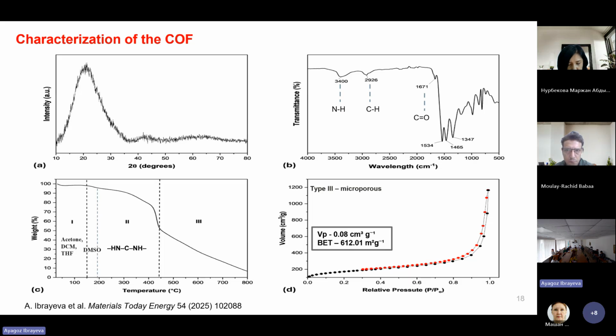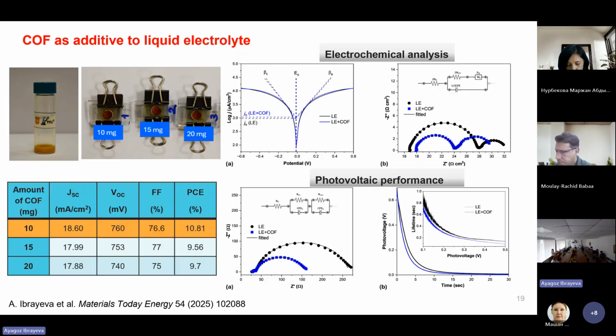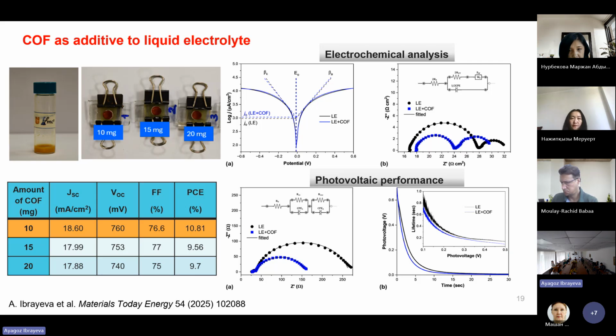BET was 612 and pore volume was 0.08. And here you can see the images of how we prepare the quasi-solid electrolyte and fabricate solar cells in our laboratory. Also, in the table we provided the optimized work, highlighted in yellow: 10 milligrams works well in our case. If we increase the amount of COF, it gives us viscosity, particle aggregation, and so on. That's why we chose 10 milligrams.